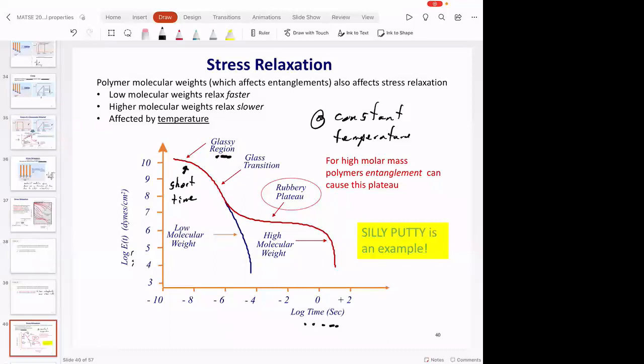So if you take a ball of silly putty and you smash it with a hammer, is that a short time experiment or is that a long time experiment? Short time experiment. And what does that silly putty do when you smash it with a hammer? It actually shatters. So if you hit the silly putty hard enough, you can get it to shatter like glass. And so silly putty, even though we experience it as a rubbery, liquidy material, at very short time, it's glassy.